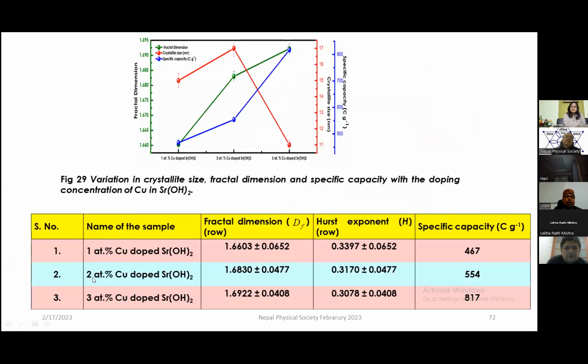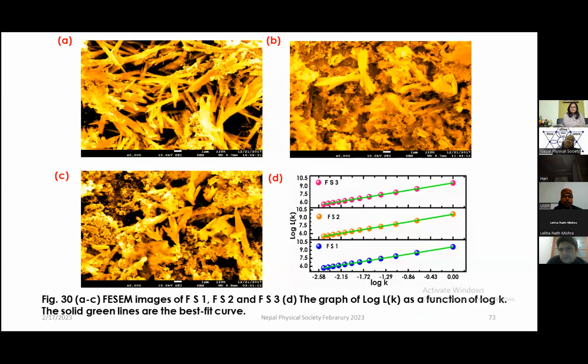So this is the copper doped one, and you can see here the value of the specific capacity that has been related with the fractal dimension. So for the different values that we have, we have this value of the specific capacity. So we have applied this fractal dimension to iron doped strontium hydroxide.